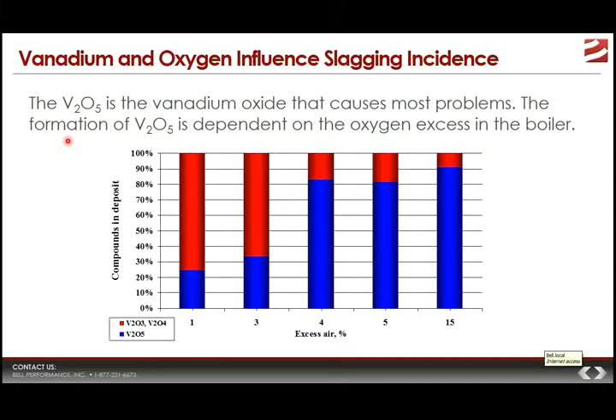When fuel burns, the vanadium oxidizes and creates a number of different vanadium oxides or vanadates. V2O5 is the vanadium oxide that causes the most problems. The amount of V2O5 that's formed is dependent on the amount of oxygen available in the boiler. As you can see from this data, you have the percentage of the different vanadates in a given deposit formed from HFO use, graphed relative to the percentage of excess air.